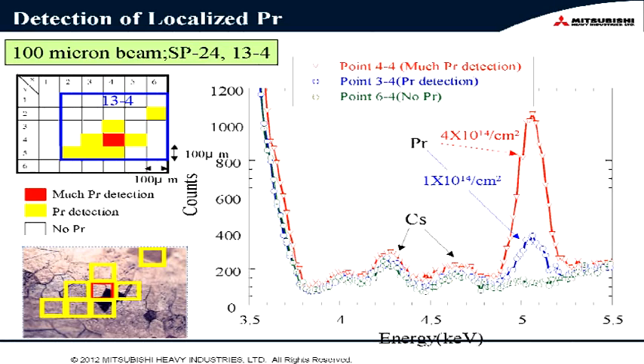This is the result of detection of praseodymium. This figure shows the surface image of the sample. The red region has a lot of praseodymium detected. This is the XRF spectrum. The red one corresponds to here and here, and we can see very clear praseodymium. In the yellow region, we have some praseodymium. But in the other regions, we do not see any praseodymium. So we can see that praseodymium is very localized.